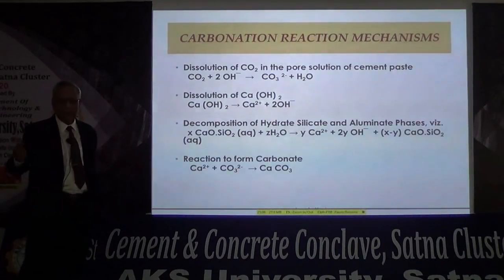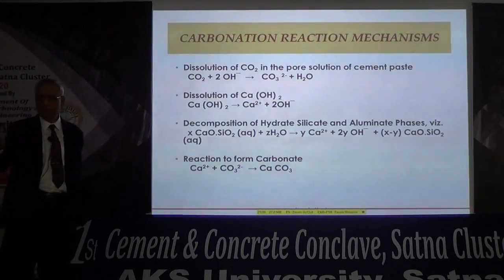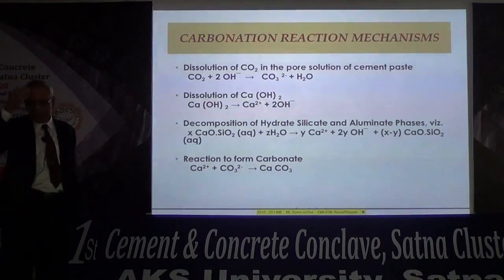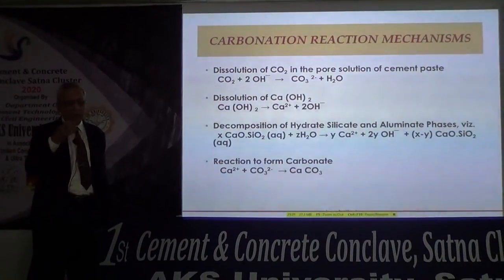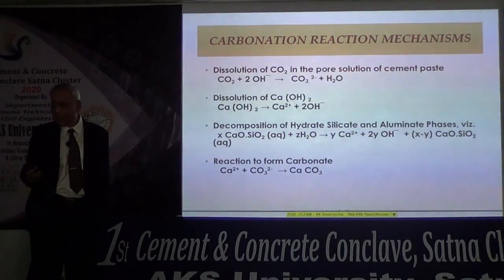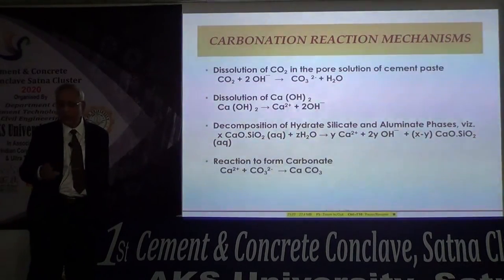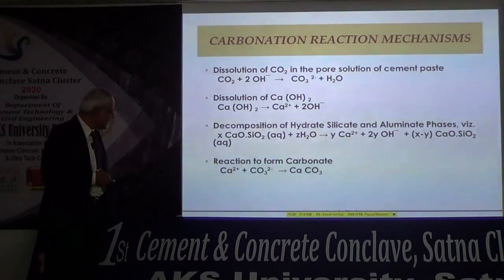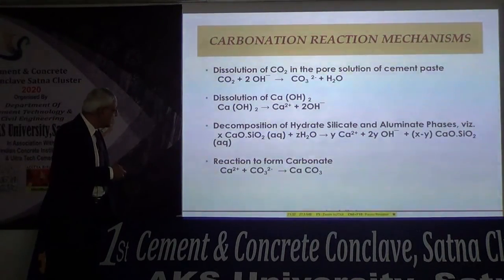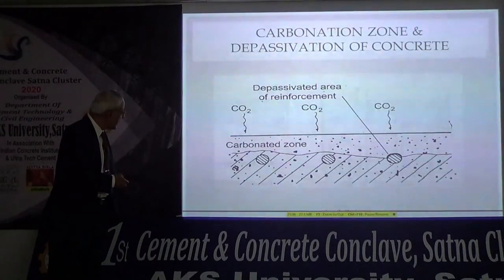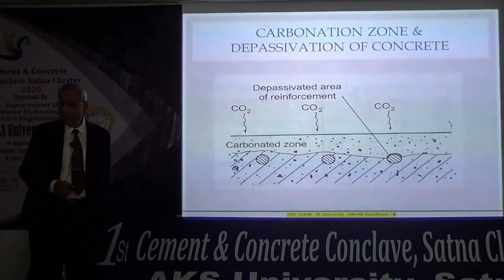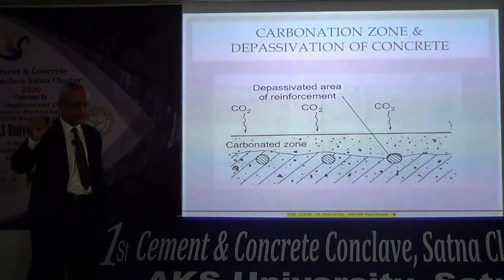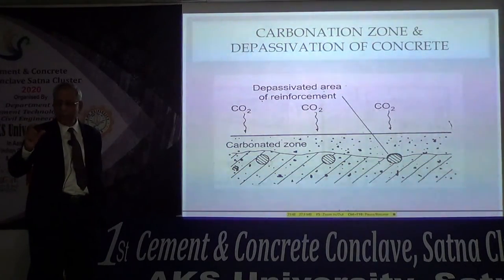Carbonation, in terms of chemistry, I wouldn't go into the details. It's a simple thing: there is carbon dioxide in the atmosphere, your concrete is not able to hold it back, and therefore it gets into the concrete, and lime is available, so you form calcium carbonate. That's why we call it a carbonation reaction. Now, without going into the nitty-gritties of this, what happens? With carbonation, the concrete cover area gets affected first.